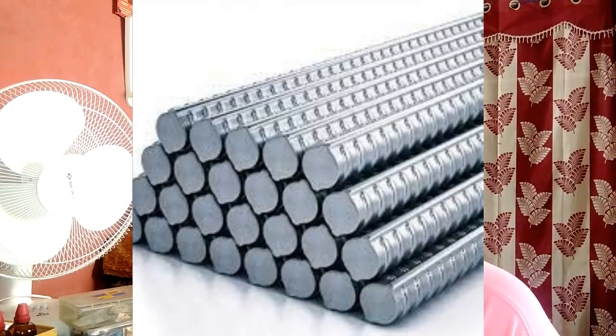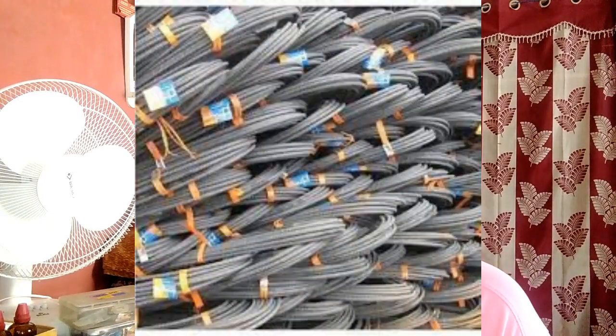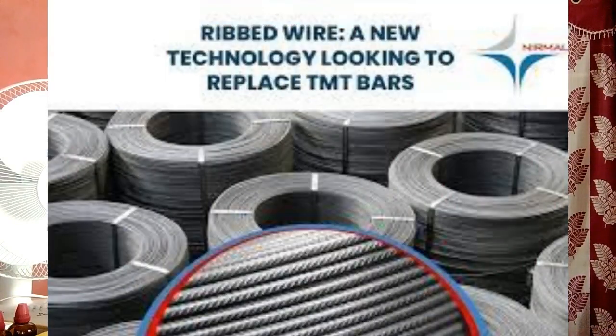Next step, the bar leaves the water quenching line and is exposed to air. The heat flux from the still hot core reheats the outer surface. The martensite formed in the first stage is thus subject to self-tempering, giving a structure called tempered martensite, which is strong and tough. The core is still